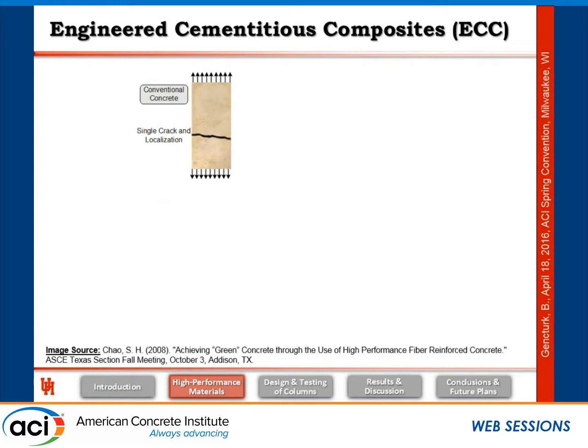So a few words on ECC. ECC is a special class of fiber-reinforced concrete. If you look at the behavior of conventional concrete in tension, obviously all cementitious materials are pretty good in compression. So if you apply compressive loads, there's usually not much of a concern. The main concern is in the tensile loading. So if you take concrete, if you apply tensile loading, this is what you're going to get. You will see a single localized crack with a brittle failure.